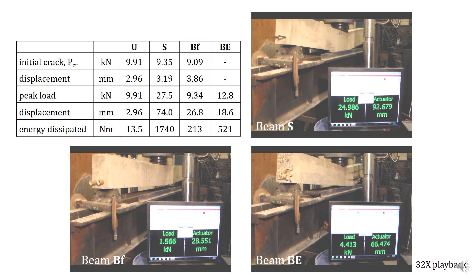Looking at the energy absorbed by each of these tests, the dominance of the steel-reinforced concrete beam is clearly in evidence, absorbing an order of magnitude greater energy than the other tests.